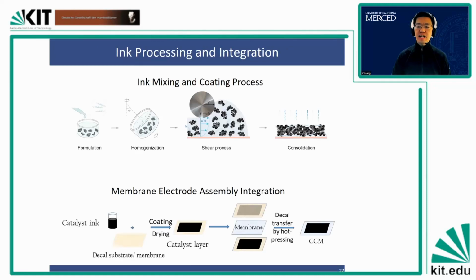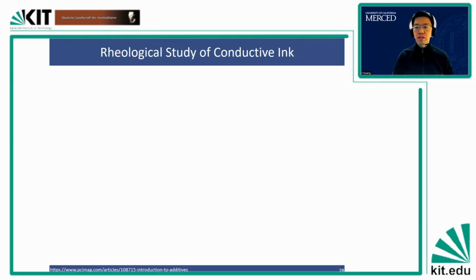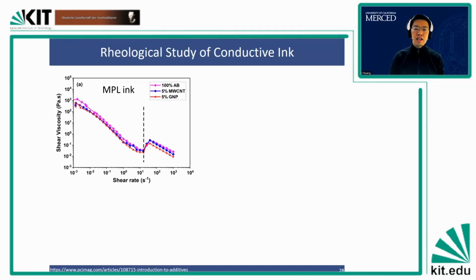But as I said, instead of just doing trial and error, where we make a recipe, then we make the MEA, we test the MEA, right? And instead of going with the trial and error approach, where we make one and then test one, knowing if it's good or bad, we actually employ a tool called rheology. So we study the rheological behavior of the catalyst ink to see, when it is under shear or before shear, what the microstructure looks like.